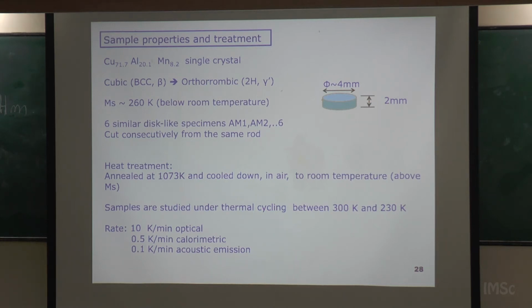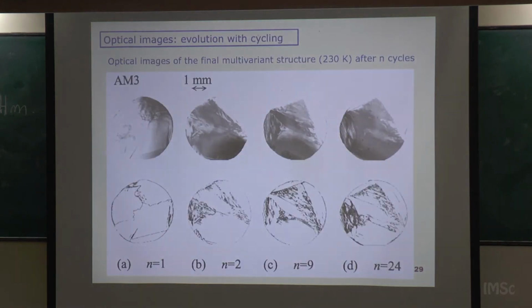And what we did is to drive the transition at different rates, and also to do what is called cycling. So usually these samples can be put in the oven at high temperature, they homogenize, and then you slowly cool down, and you have what is called a virgin sample. Then you start, but still without crossing the transition, and then you start to cross the transition, back, forth and back, forth, and then you study what happens when you cycle, okay? And this is just to show how the acoustic emission can reveal details of how this transition is advancing, okay?